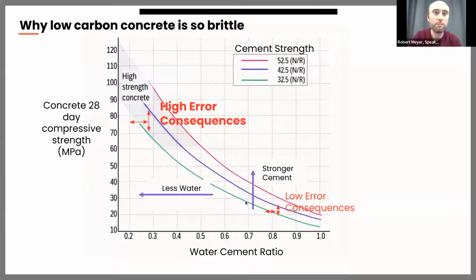But if I'm operating up here in this low water, high strength regime, what you can see is that the curves are farther apart and also the slope is very steep. Any error I make will have severe consequences. If I get my water dosage wrong, that has severe consequences on the resulting strength. If the cement strength is not reliable, this will also have severe consequences on the final strength of my concrete. So everything up here is really difficult to produce.